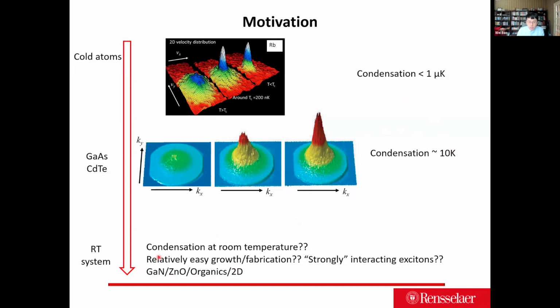And as I said, there's condensation at room temperature, but no system has really good growth or fabrication while at the same time having a linear mode where the exciton exists. Gallium nitride, zinc oxide, organic, 2D, all this past effort at room temperature seems to generate really poor results compared with gallium arsenide or cadmium telluride.